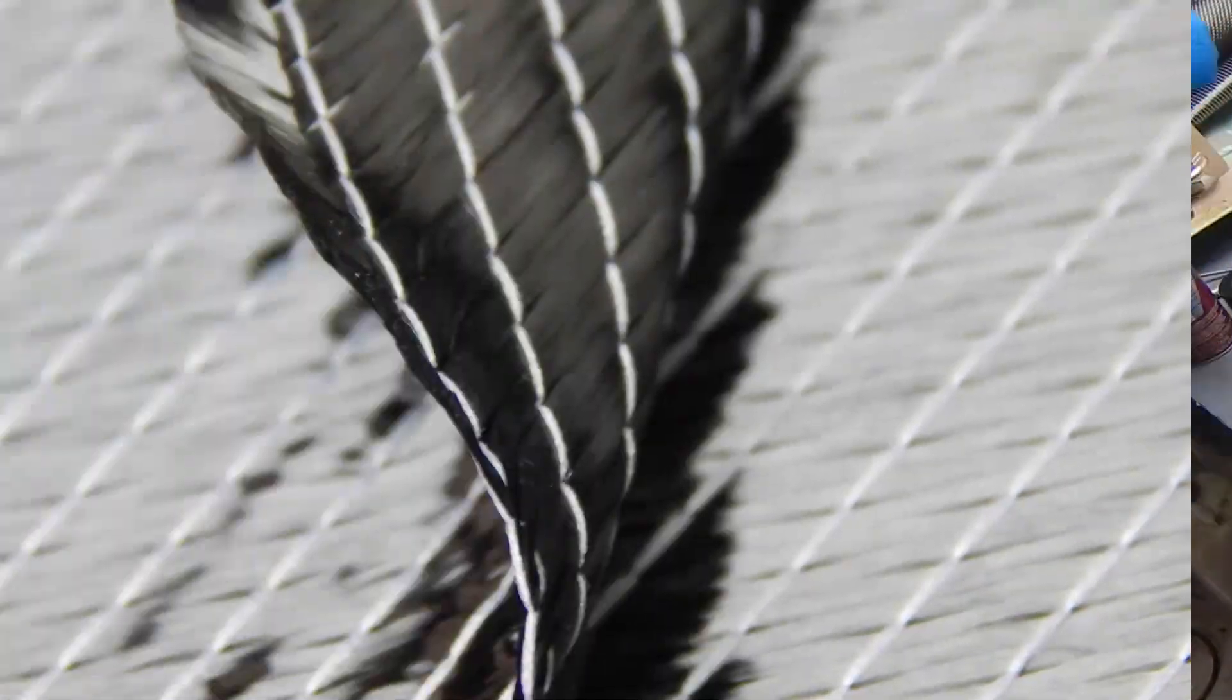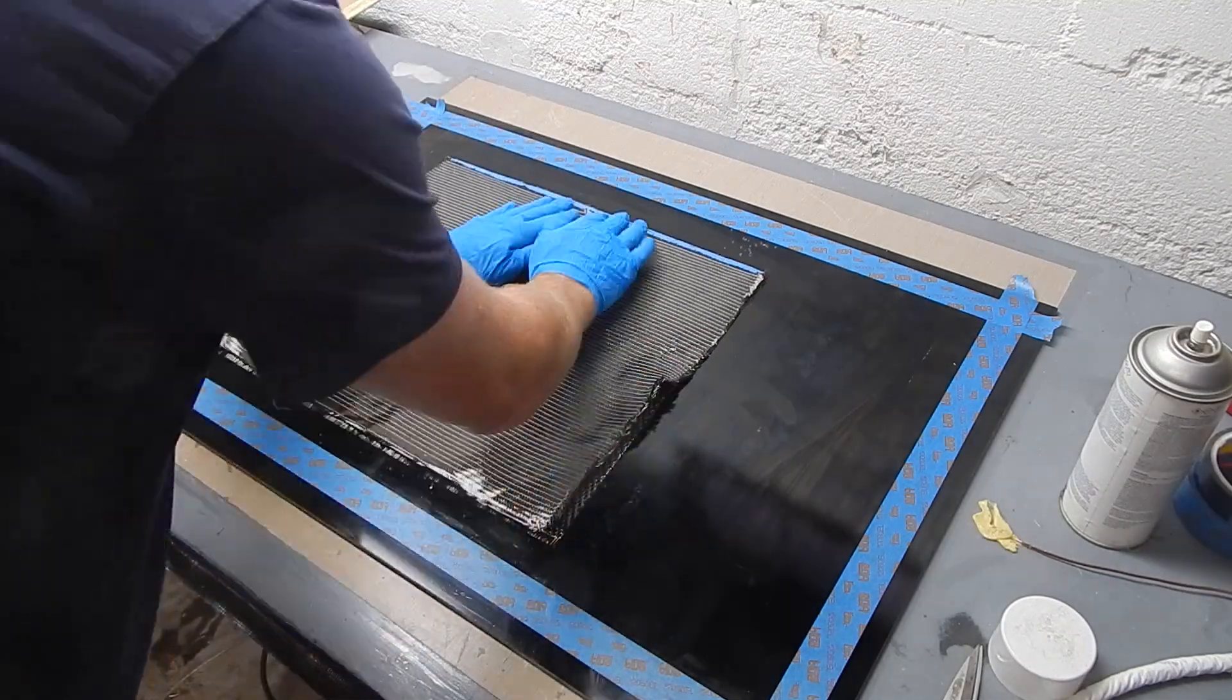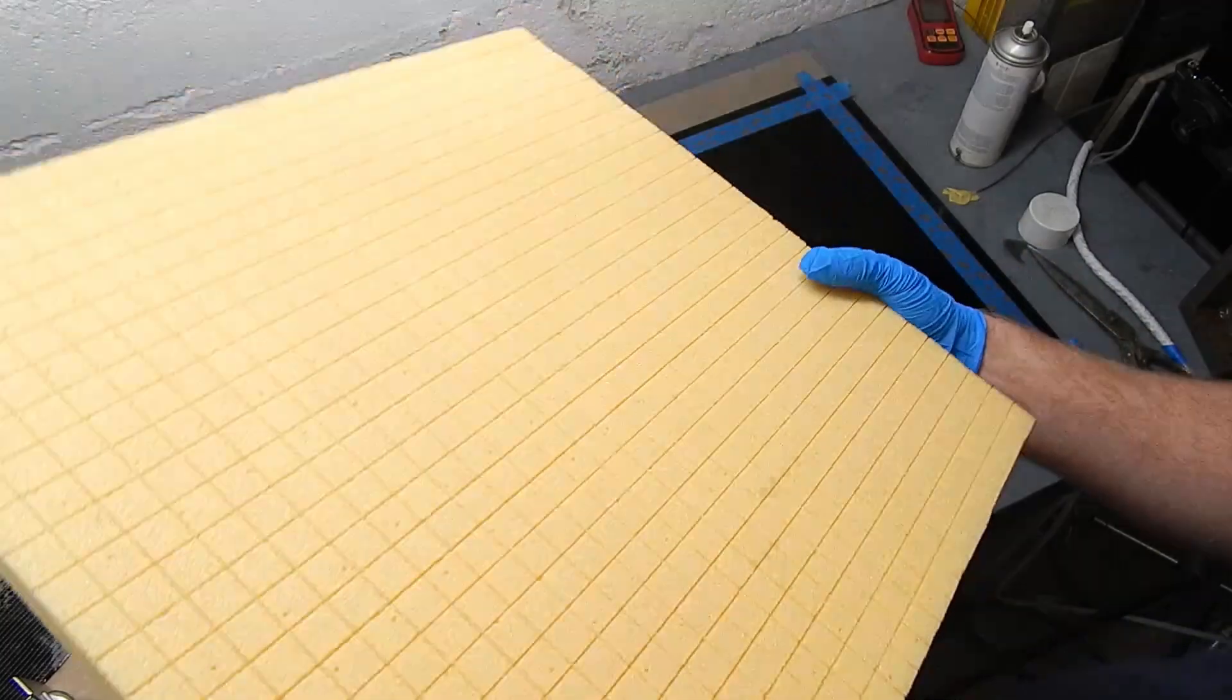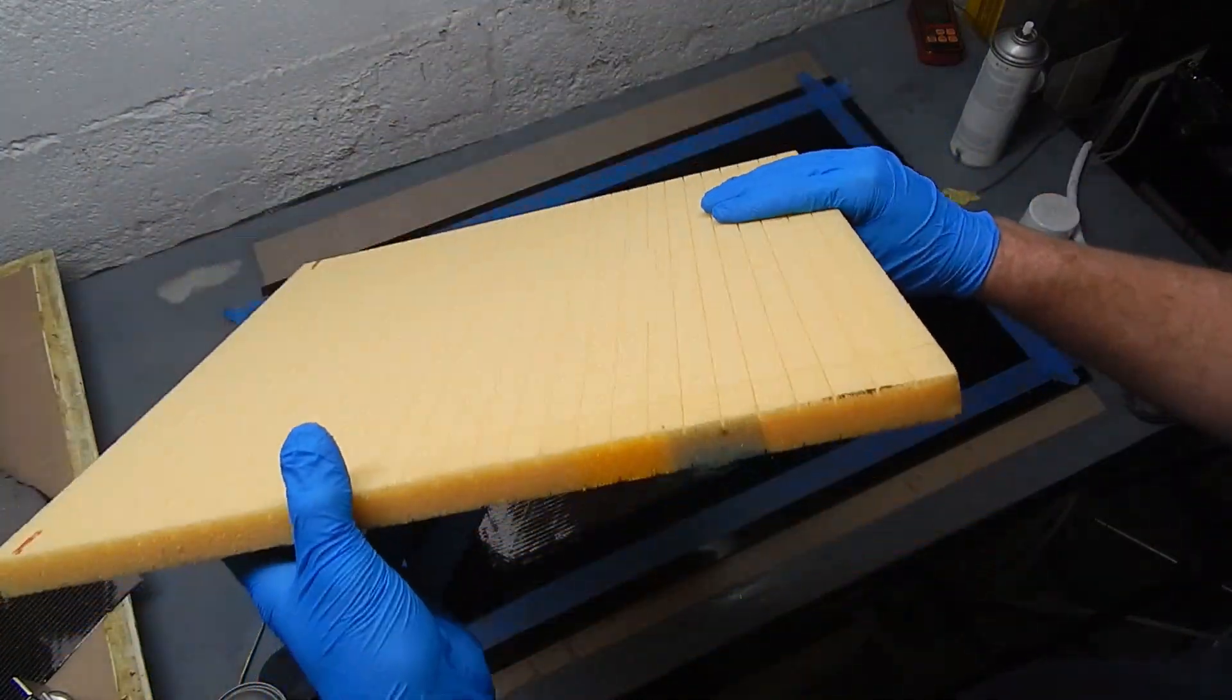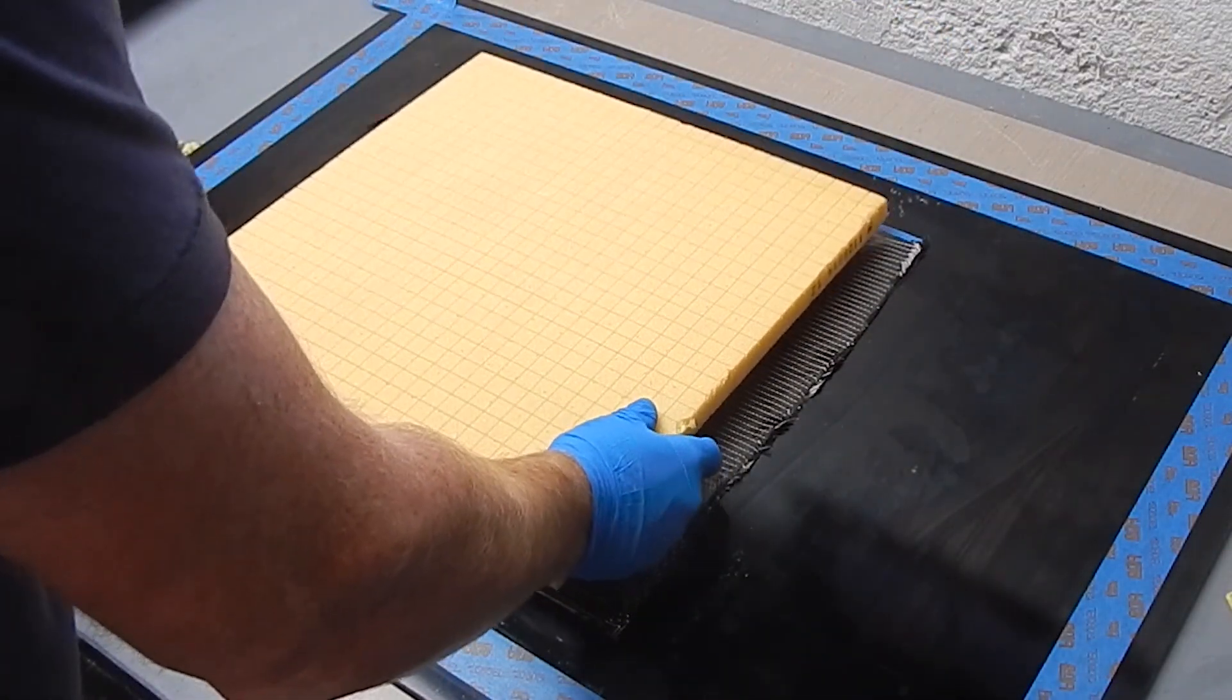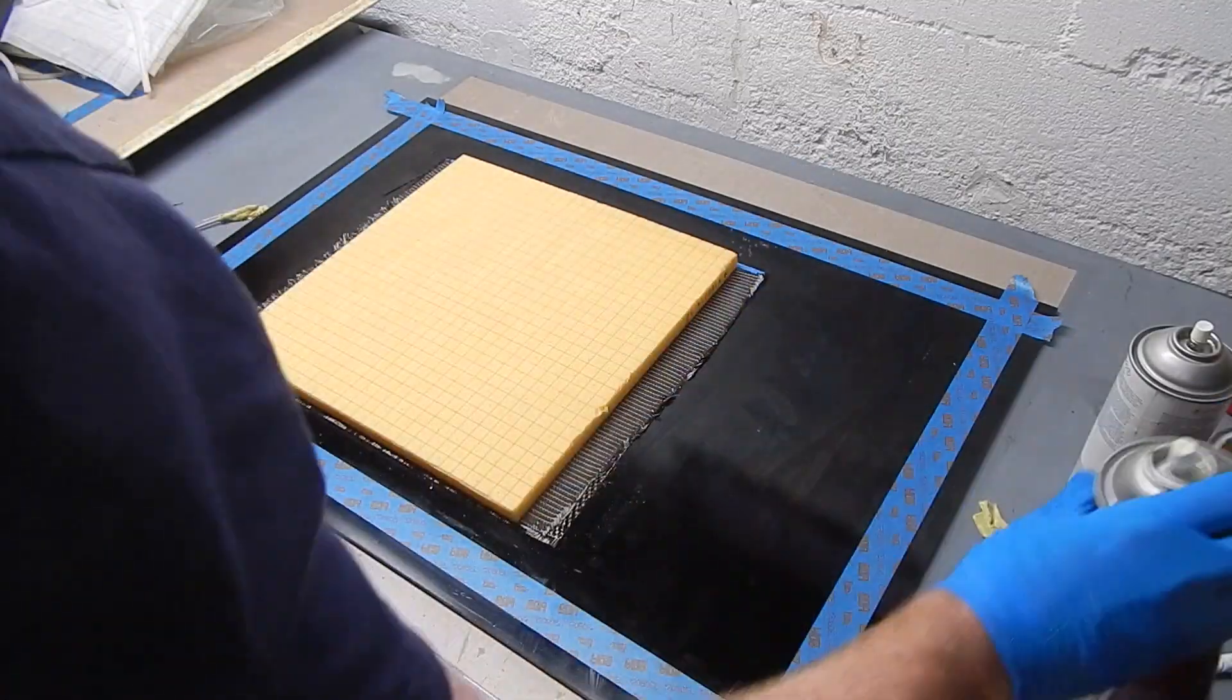Here's a look at the bi-axe, which is the second ply facing the core. This is also 400g, it's a stitched material, it's really just two unis attached together. And here's the core, you can see the flow grooves, it's also perforated, so the resin can flow through the core. And I'm going to just place this down on that first skin, and now, working symmetrically about that core, place the remaining plies to form the sandwich here.